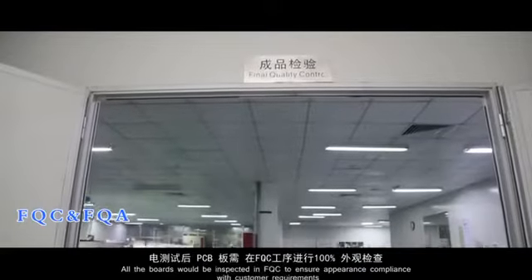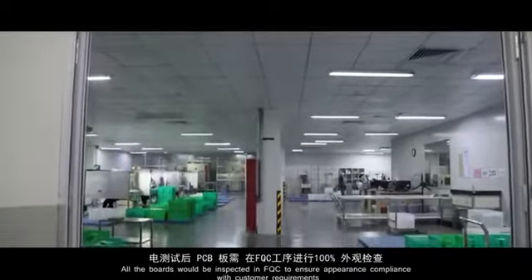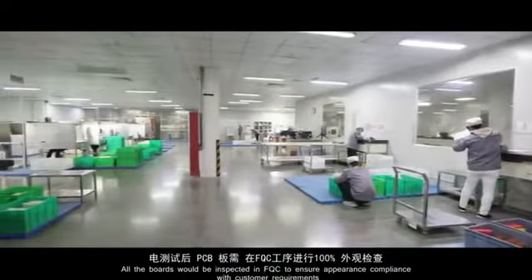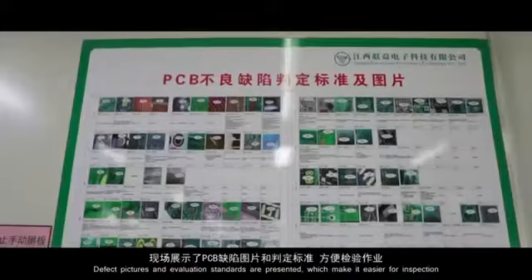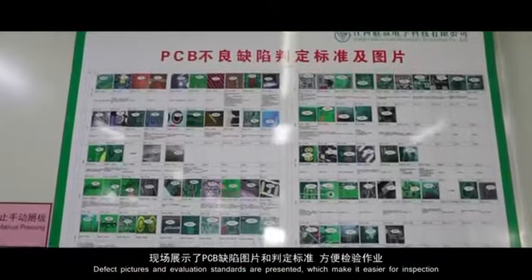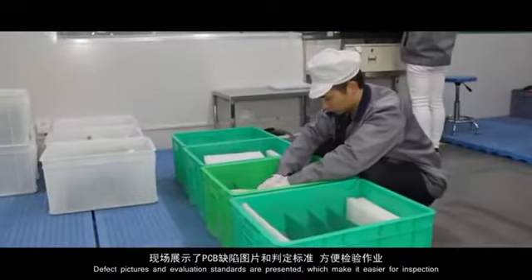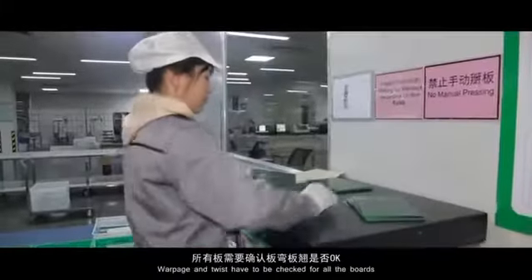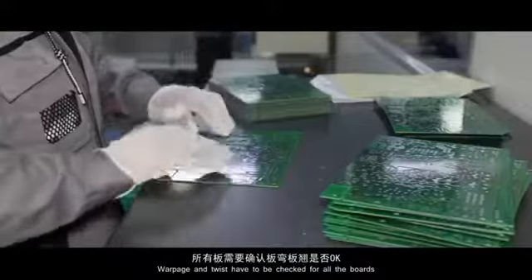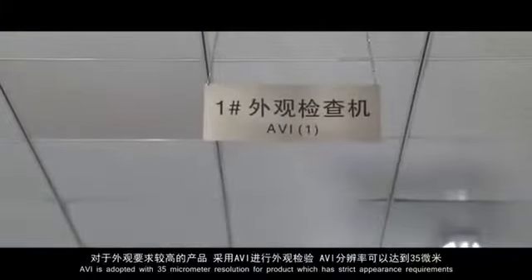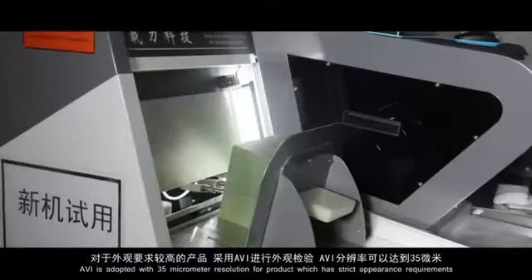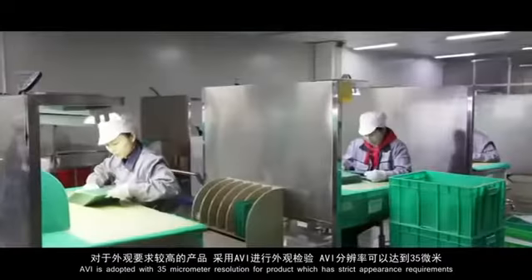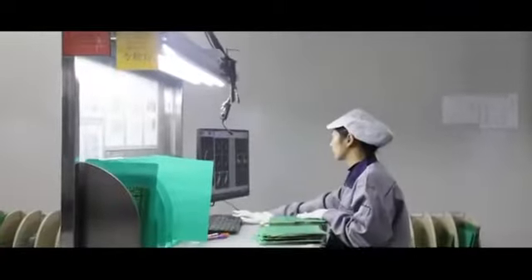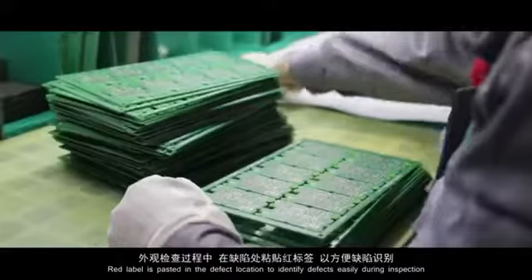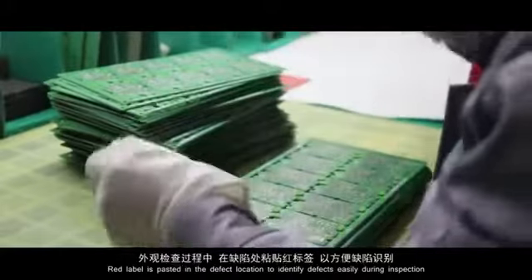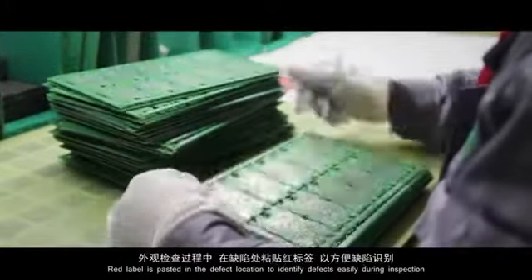All the boards would be inspected in FQC to ensure appearance compliance with customer requirements. Defect pictures and evaluation standards are presented, which make it easier for inspection. Warpage and twist have to be checked for all the boards. AVI is adopted with 35 micrometer resolution for products which have strict appearance requirements. A red label is pasted at the defect location to identify defects easily during inspection.